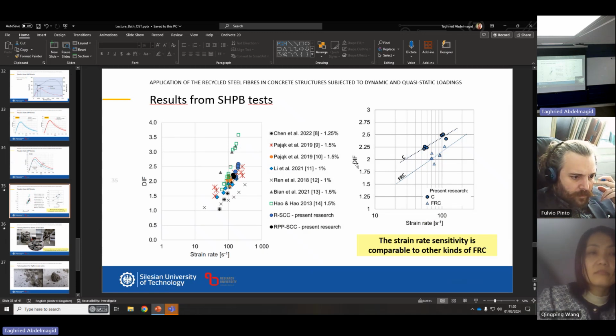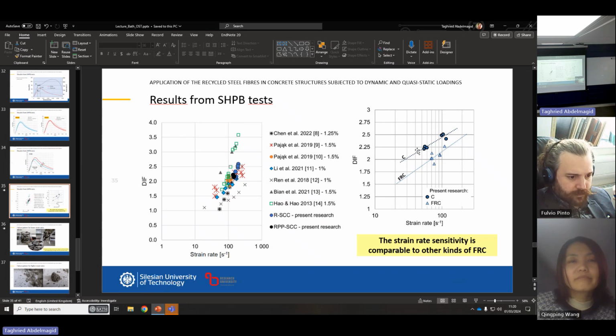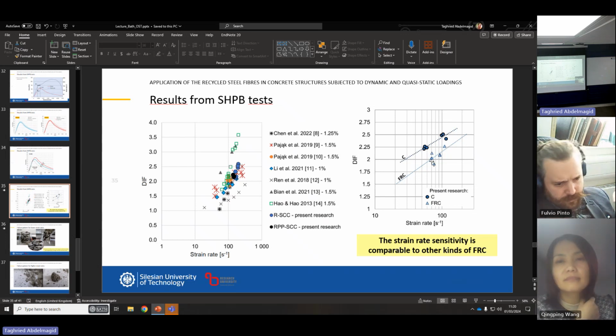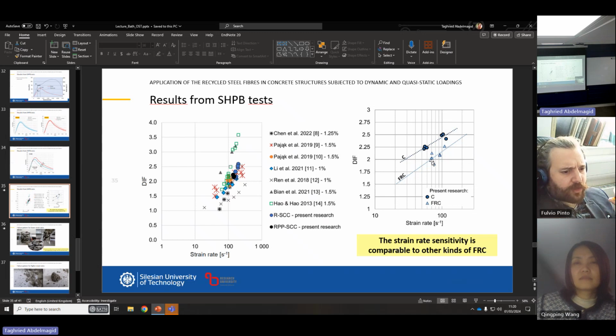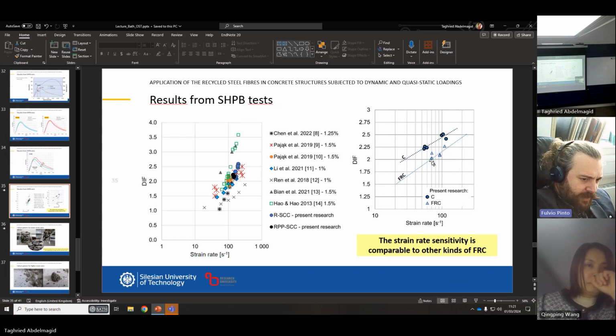This DIF is the comparison of the dynamic strength to the quasi-static strength. So we have this huge increase for concrete, and for fiber reinforced concrete it's lower. So this is for sure that we achieve it, no matter the radial forces and so on. It's lower, but the gradient seems higher. So it seems to me that the effect of the increasing strain rate is higher for the fiber reinforced concrete than for the normal concrete.